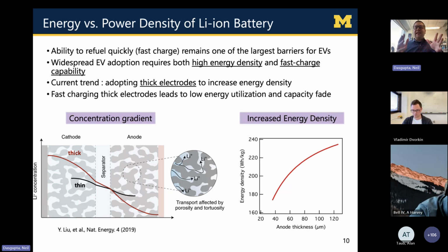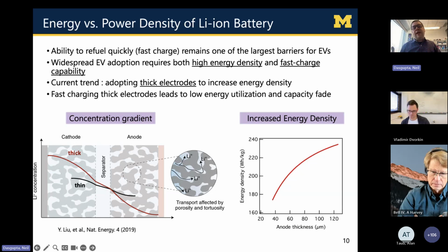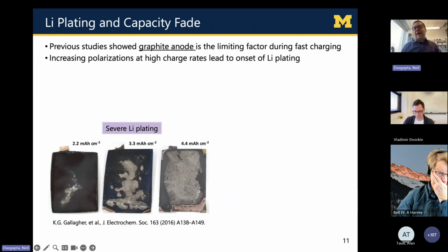But this is one of the things that inherently results in this trade-off, because as we go to thicker and thicker electrodes, while that increases the energy density, as we can see on the right-hand side in this graph of energy density versus the anode thickness, the ability to move lithium ions in and out of these thick electrodes becomes increasingly challenging. And that's what you're seeing on the left-hand side. You form these concentration gradients in the electrode that really prevent fast charging from being possible.